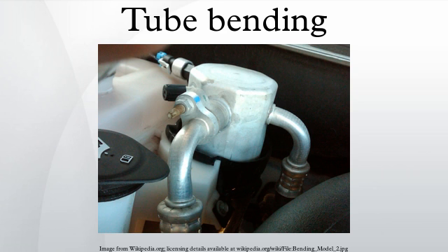Heat induction. An induction coil is placed around a small section of the pipe at the bend point. It is then heated to between 800 and 2200 degrees Fahrenheit. While the pipe is hot, pressure is placed on the pipe to bend it. The pipe is then quenched with either air or water spray. Heat induction bending is used on large pipes such as freeway signs, power plants, and petroleum pipelines.